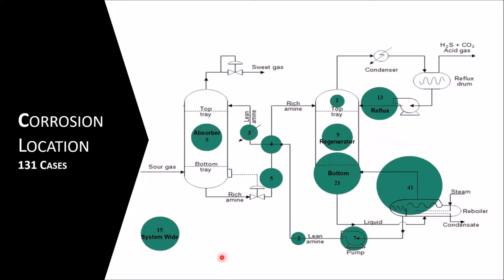So this is a really interesting part of the database: where exactly did the corrosion occur? I'm going to start here at the bottom where it says system-wide 15. So out of these 131 cases, only 15 are what we would consider system-wide, which means there was corrosion in the reboiler and the absorber and piping, and it was all over. Not all from the same mechanism, but they had system-wide corrosion.